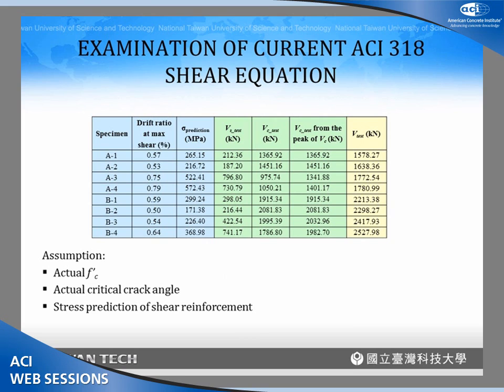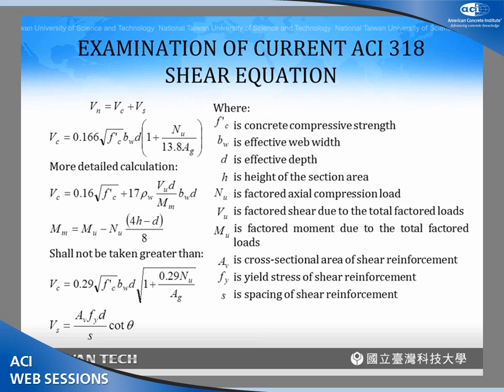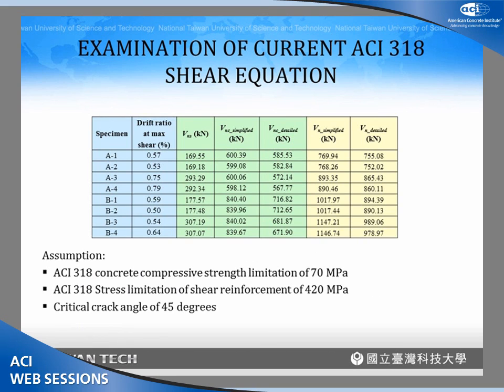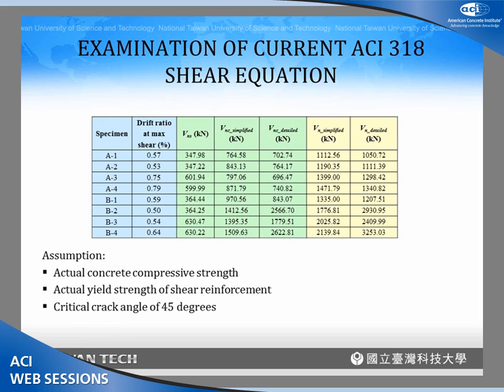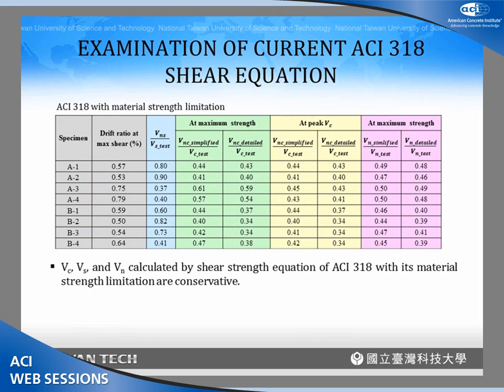So this table shows you the Vc, Vs, and Vn for all the specimens from the test result. And we try to compare the test result with the ACI shear strength equation. We know that the Vc equation has a simplified version and a detailed version. So this is the ACI shear strength calculation result, assuming the maximum f'c of 70 megapascal and maximum fy of 420 megapascal, and assuming a critical cracking angle of 45 degrees. Let me jump to the result.